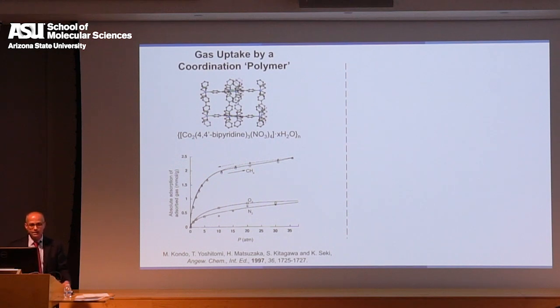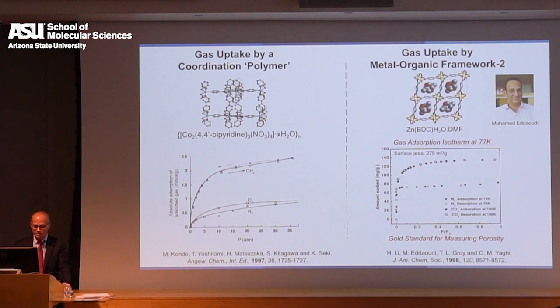These authors are saying that they prove porosity. That doesn't prove porosity, especially since from this data, you cannot get the porosity data, which is surface area and pore volume. You can't use this data to do that. You need the gas adsorption isotherm.